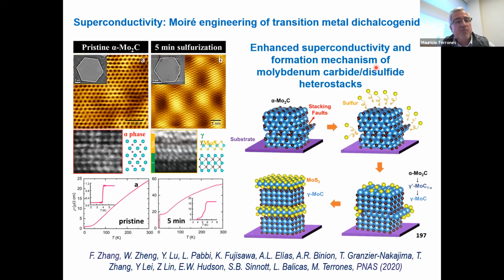So the way this is happening, again, when you have the stacking folds, you have the H2S system. And we first start transforming with the sulfur, we start transforming and straining this alpha molycarbide into gamma prime molycarbide, and we start getting some monolayers of molysulfide. And then we transform this phase into gamma. So these are some transformations that go through, but I think this stacking of different layered systems, it's very neat. So this is something that we're working on with other systems, and hopefully we can